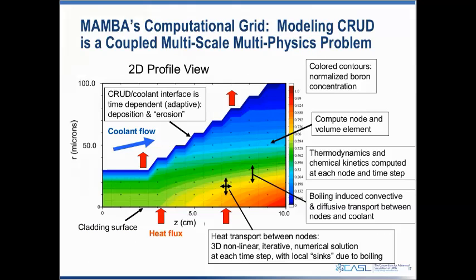On this slide I'm going into more detail about the computational approach used to model CRUD. Here's the grid again. The radial deposition of CRUD deposits on the surface. MAMBA uses an adaptive mesh or grid that grows as the CRUD layer grows. This growth is determined by the temperature of the cladding surface as well as the concentrations of particulates such as nickel and iron in the coolant, which come from corrosion elsewhere in the primary circuit, as Jeff mentioned previously.